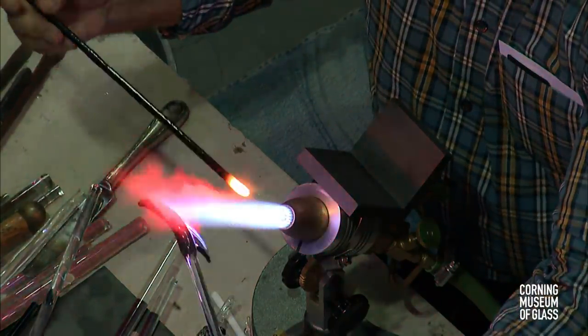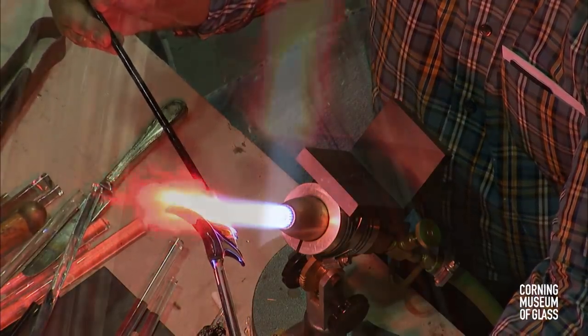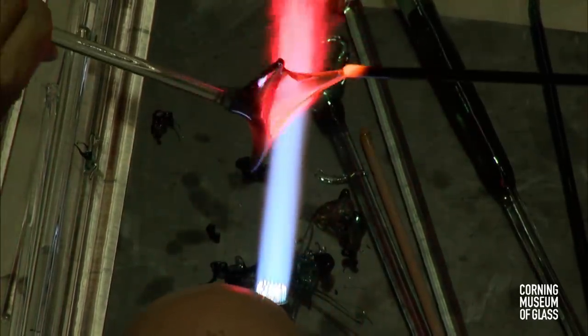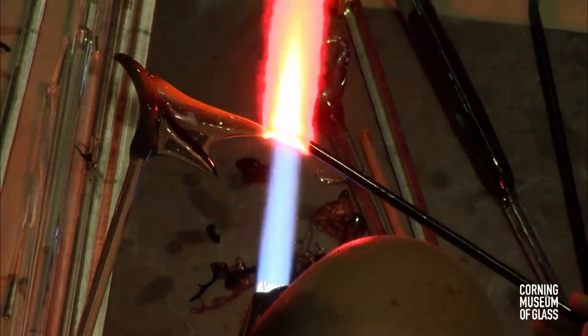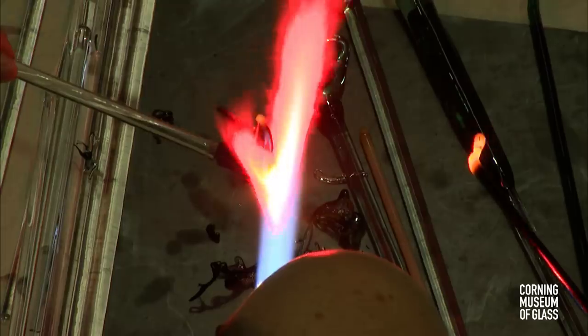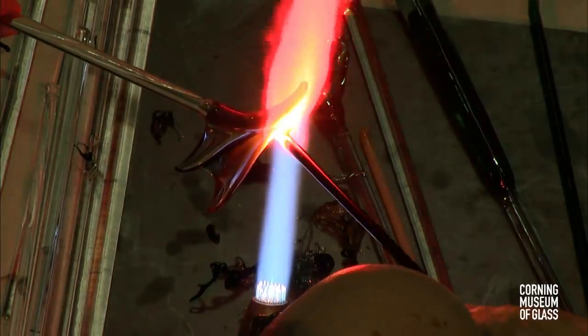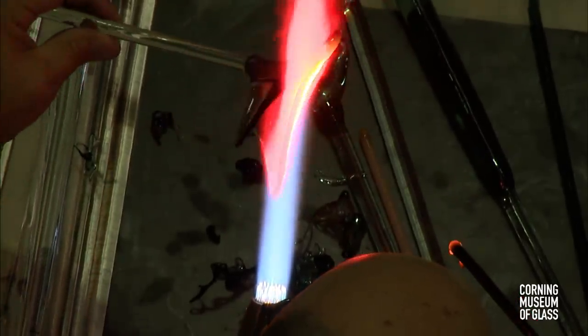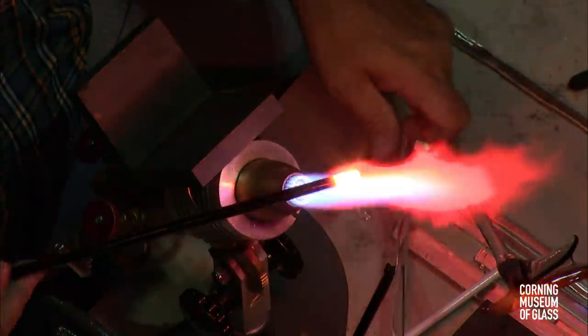So you notice David sort of cleaning off the tips of those colored glass rods every once in a while. It's almost like cleaning off your paintbrushes as you're about to move to the next step. And one particular thing with nipping off the tip of this rod here, he just picked up a fresh rod of colored glass. The end of that rod had been snapped apart. And anytime you heat into a broken edge of glass with a torch, it wants to boil and bubble. So by stripping off the end that was broken, he gets to glass that is not going to boil and bubble so easily. So that's why we sort of trim off that end, make sure he's working with nice, clean glass, so we don't incorporate any sort of scum or any unwanted bubbles into the sculpture itself.